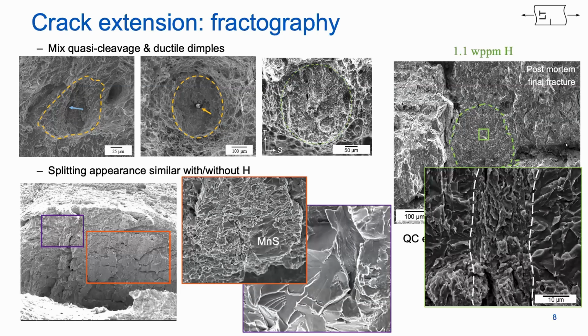For the splits I mentioned, there was no real trend with the lower hydrogen concentration, and this bears out in the appearance. The splits always look like a mix of this very fine faceted region with the MnS, which is of course the bainitic bands, which had the flat MnS, and also very large facets, which are probably large ferrite grains, which are also in the vicinity of these bainitic bands. So clearly splitting in these specimens is associated with the segregation region.